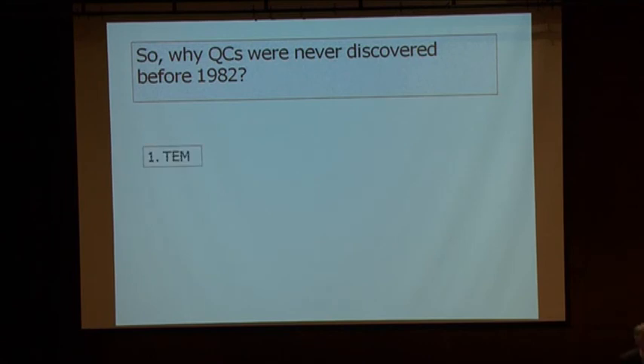Answer number one, TEM, transmission electron microscopy. Quasi-periodic materials could not have been discovered but by an electron microscope. Why so? Because the crystals were very, very small. My crystals were 2 microns in size, and so were all the crystals. Even though people tried to grow large crystals, it took 3 years for somebody to grow a large enough crystal, which was like a grain of sand, in order to take the first X-ray diffraction. So TEM should have been the tool. That limits the number of researchers that could find quasi-periodic materials.